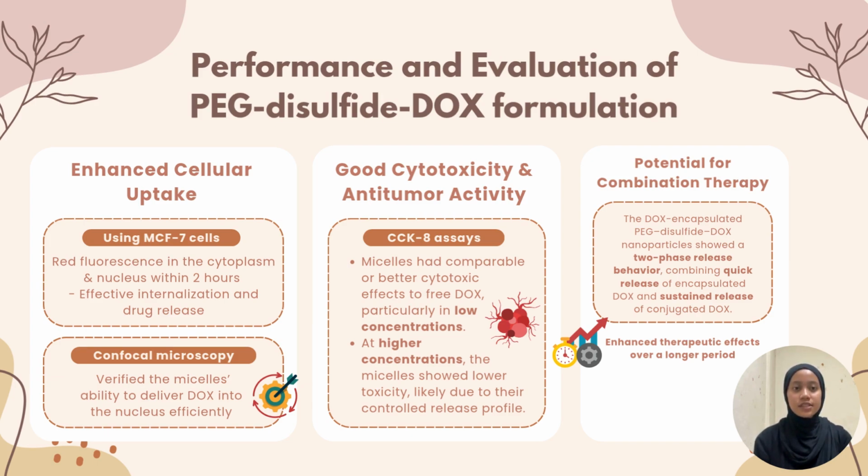Next, the micelles showed similar or better cytotoxic effects than free DOX at low doses. At higher concentrations, reduced toxicity was noted, likely due to the controlled drug release. These results were confirmed through CCK8 assays. Lastly, the formulation showed promise for combination therapy. It displayed a two-phase release, an initial burst of free DOX followed by sustained release of the conjugated form, offering extended therapeutic action over time.